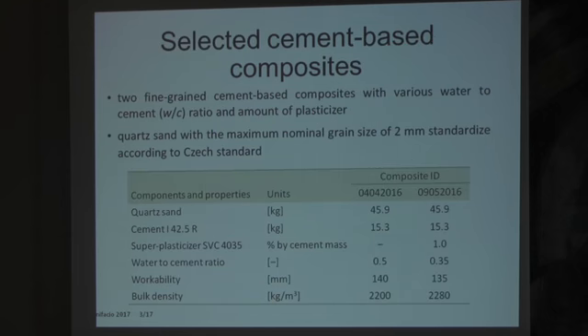So, about the experiments. For the study, we selected two fine-grained cement-based composites. In the table, you can see the composition of these two composites. The amount of aggregate was the same, in this case only normalized quartz sand with a maximum grain size of 2 millimeters, and the same for the cement. The amount is the same in both mixtures. The difference is in the water to cement ratio, and the second mixture also contains a superplasticizer admixture. You can also see the basic parameters of the fresh mixtures, workability and bulk density of these materials.